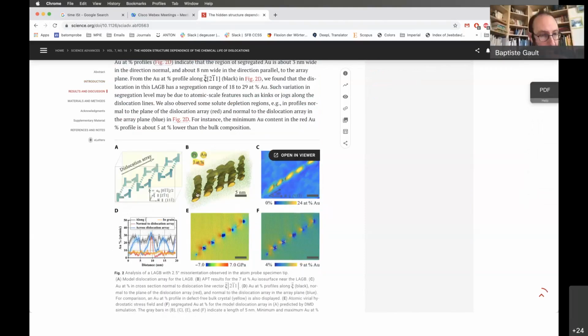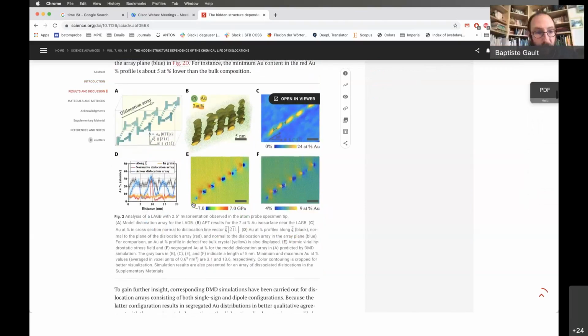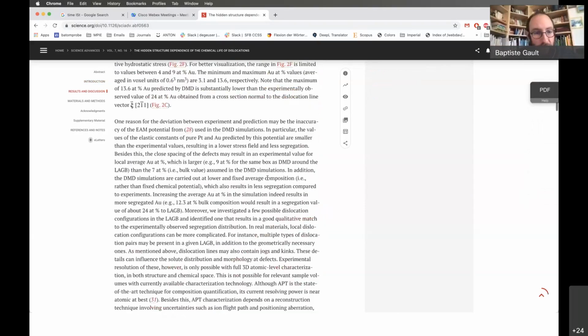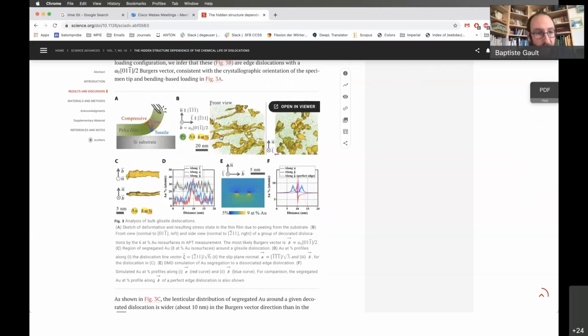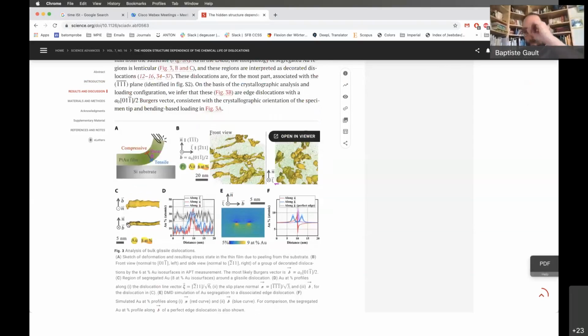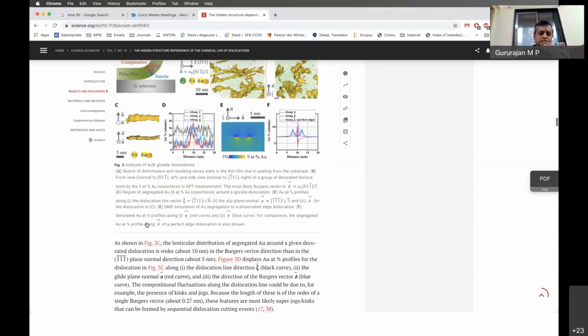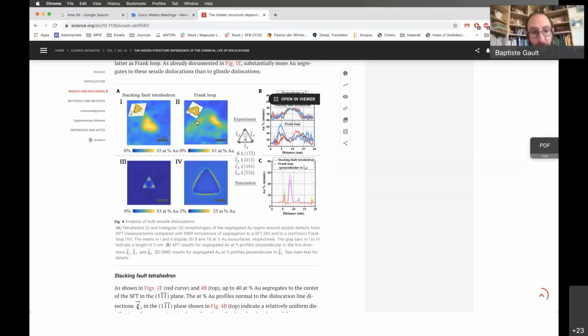Here you can see a low angle boundary, for example, with the segregation on the split dislocation of whatever width. And then we did some comparison with the atomistics. Then you see some stacking faults and some Thomson tetrahedra and all of this. You can measure locally what is the composition of these different beasts, and they're all a bit different. Some of them will be really like a tiny tube. Some of them will be split with segregation on the faults and on the partials. And you can see here, that's one of these stacking fault tetrahedra with segregation on. Nice. Yeah, it's really beautiful work. But it goes to show the strength of the technique when we do things properly.